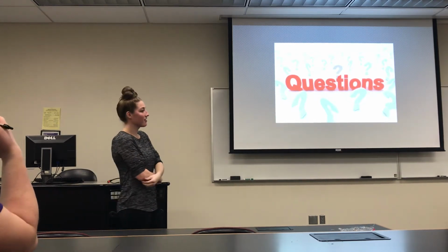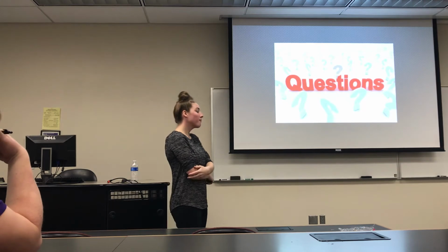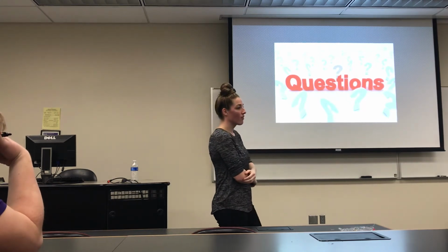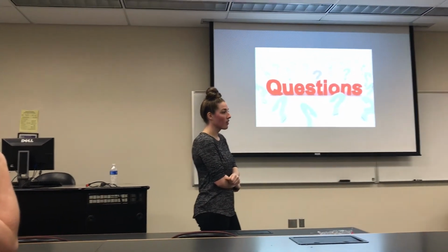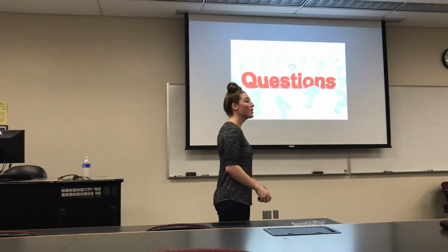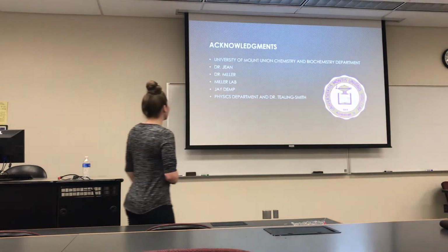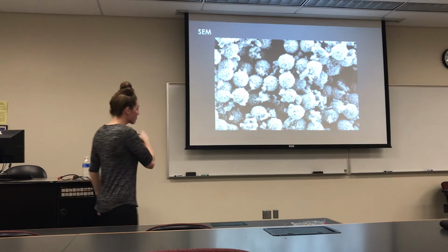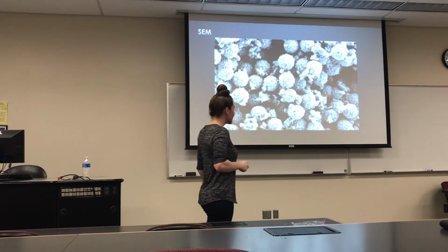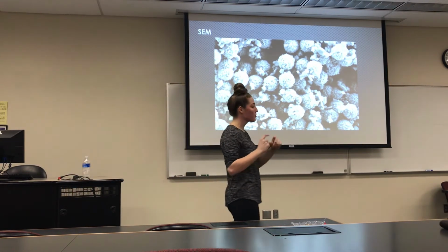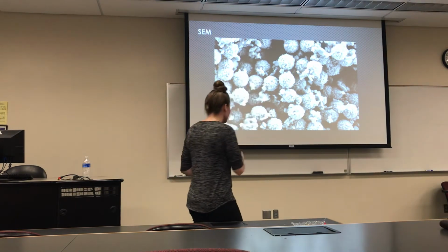So whenever you went to make your palladium nanoparticles, did you also do like three reductions? Yes. There you go. No. So if I go back to that, this was sort of what I was talking about before. We didn't get shell formation. The solution I used was so concentrated that I was actually able to get full shell formation.